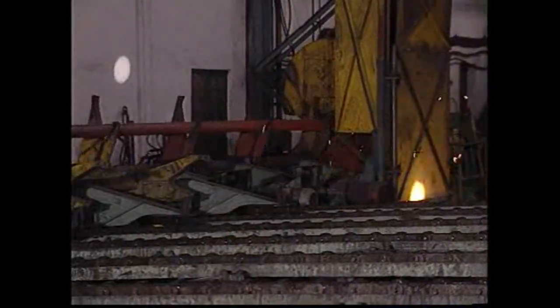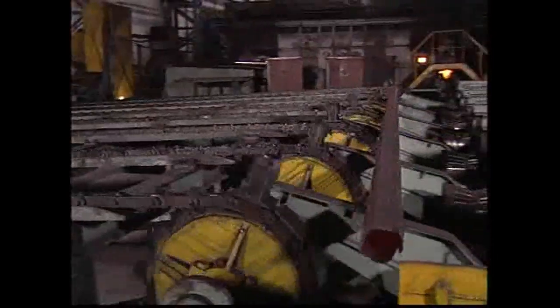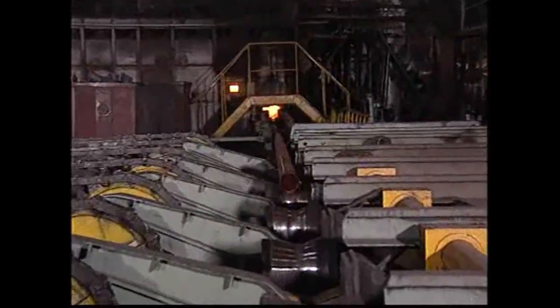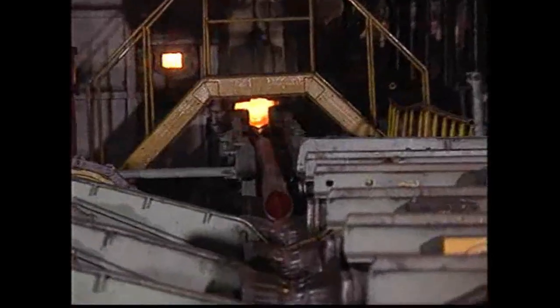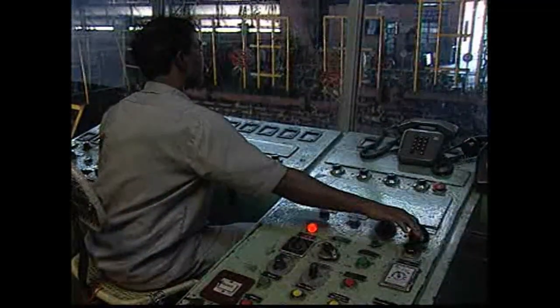A circular rotating saw frees the shell of its closed end and the shell proceeds into the walking beam furnace which has a capacity of 25 tons per hour. The shell is reheated to 950 degrees centigrade, descaled by water jets and is further reduced in diameter in a stretch reducing mill.